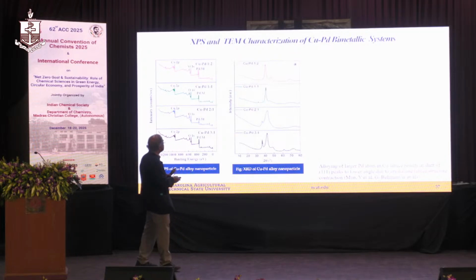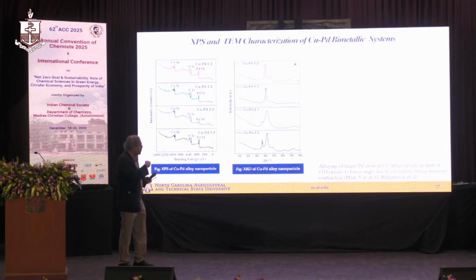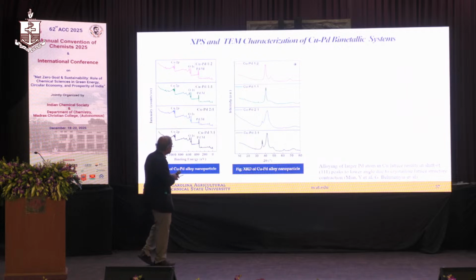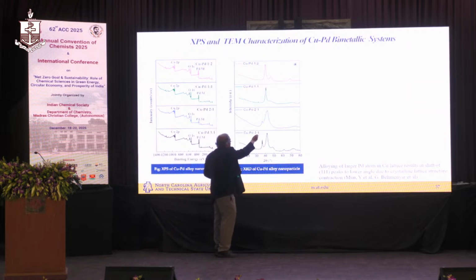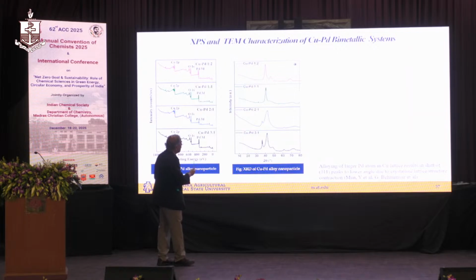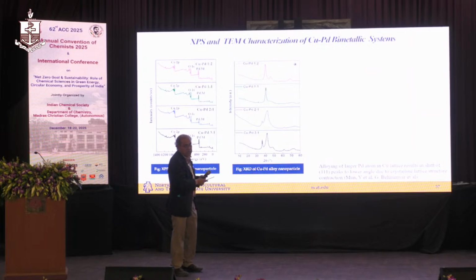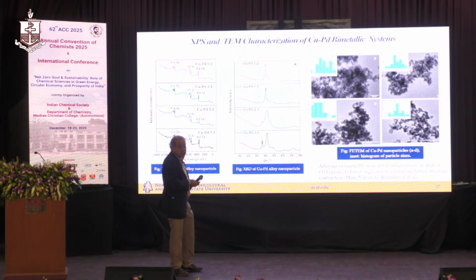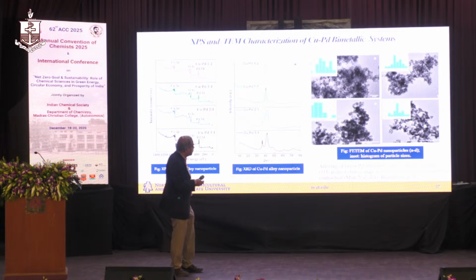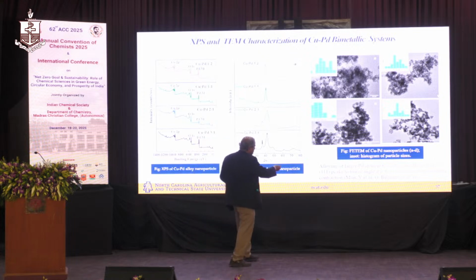And so here I show you the XPS, X-ray photoelectron results of this 1-to-1 and the 2-to-1 and 3-to-1, and you can see it's an alloy formation. Then you can see these peaks, and the XRD peaks actually move a little bit because of this alloy. It's not exactly at the same point. Okay? That is good. That's how we know that you are forming the alloy. And then you can look at the TEM image. This is the field emission TEM image with a histogram of the particle size, and you can see a shift of the peaks to the lower angle due to this crystalline lattice structure.